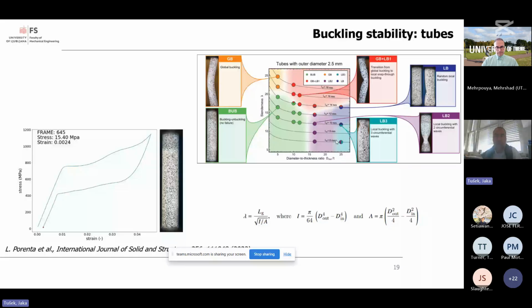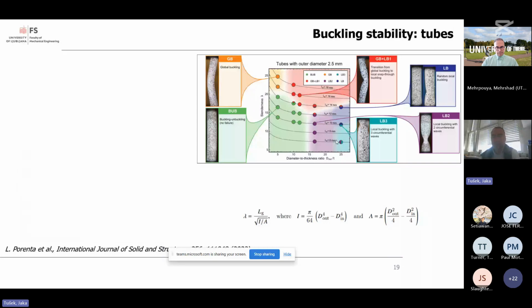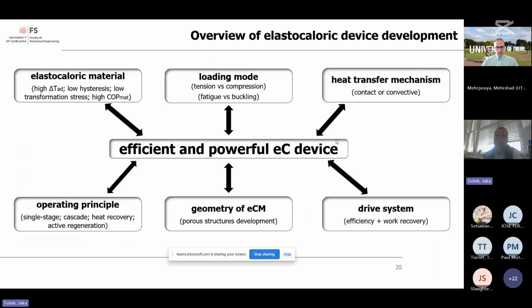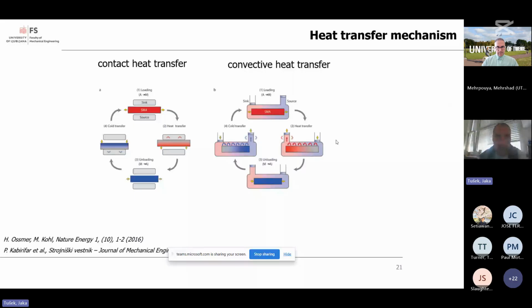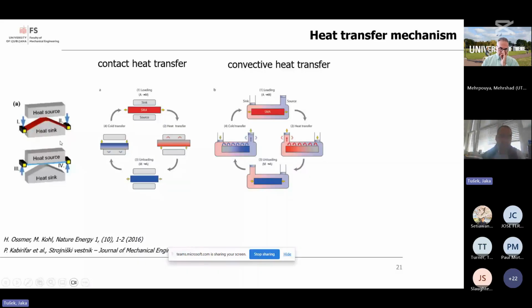Okay, so let's go further. Let's talk briefly about the heat transfer mechanism. In principle, we can distinguish between contact and convective heat transfer. This plot shows two cycles, one for contact and another one for convective heat transfer. In both cases, there are 4 basic operational steps, which are loading and unloading, and in between those steps, there is a heat transfer process. In the case of contact heat transfer, you apply mechanical contact between the elastocaloric material and the heat sink and heat source.